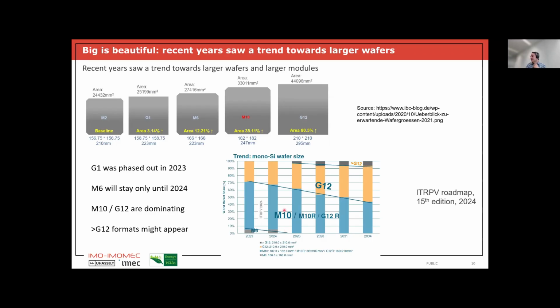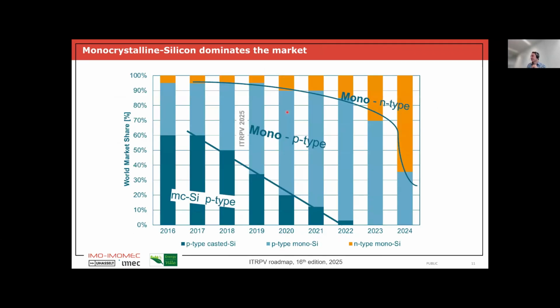And so you see here in this graph from the ITRPV roadmap, the market share of the different wafers. So at the moment in 2024, 2025, everybody in industry is basically using these very large wafers. And here we see a little bit the evolution over time, over the last decade, of what type of silicon wafers have been used. So you can see if we go to 2016, 60% of the market was based on multicrystalline silicon. So this is a slightly cheaper silicon wafer, but it has grain boundaries. It has many defects inside, so you cannot really go to very high efficiencies with this type of wafer. And as I explained, we really need highly efficient PV modules.